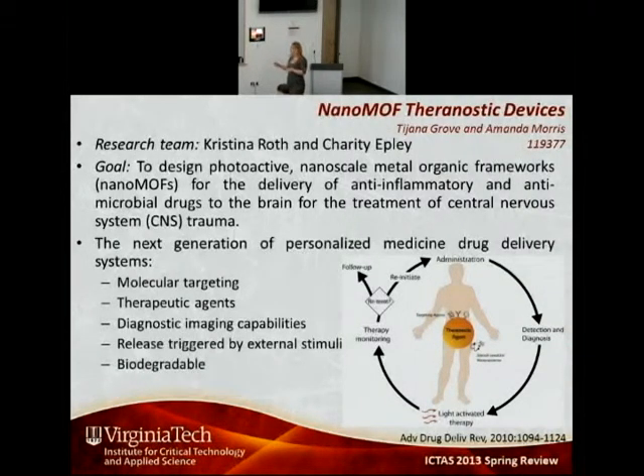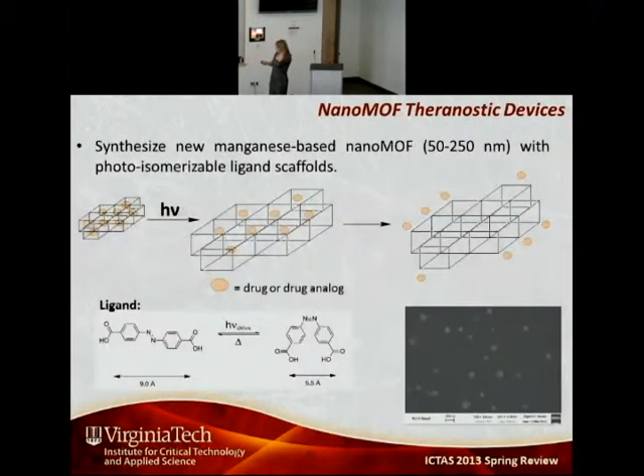NanoMOFs are metal-organic framework nanoparticles, and they're actually very different from all the nanoparticles that we've seen so far. In the metal-organic nanoparticles, we have metal centers that are connected by organic ligands, and through different synthetic procedures, you can modulate the size of the nanoparticle. In order to impart some kind of external stimuli responsiveness to this kind of particle, we thought about using, as the organic ligand, molecules that will isomerize upon irradiation. This figure is in a sense a little misleading, but the idea is basically that.